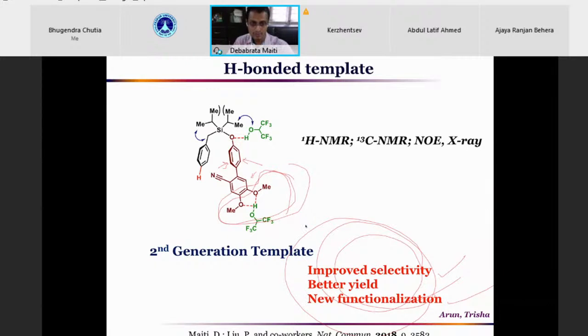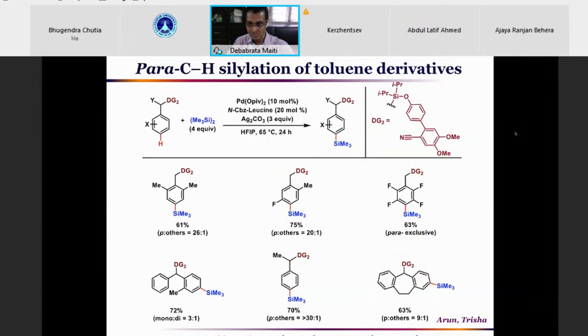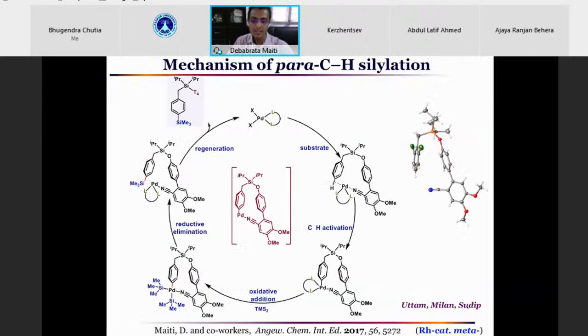Of course, there is hydrogen bonding from the hexafluoroisopropanol solvent, which makes the reaction better. With this ligand, the second generation template, which essentially has the dimethoxy group, we can do these reactions with very good yield and moderate to excellent levels of selectivity. The reaction mechanism is relatively simple, as you may have imagined. The metal is bound with respect to the directing group in such a way that the metal is positioned perfectly with respect to the para-CH bond, and it's getting activated and metallation is happening selectively at the para position.